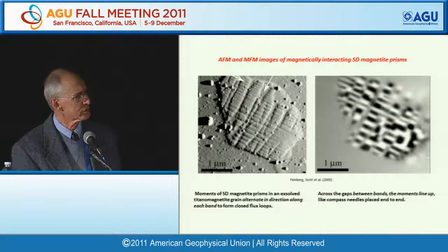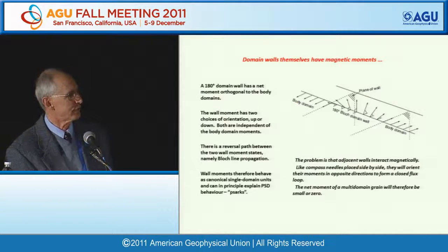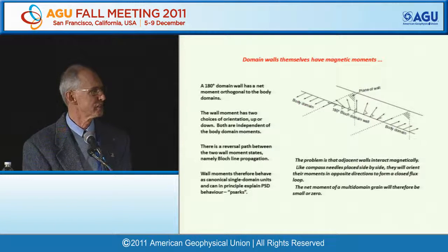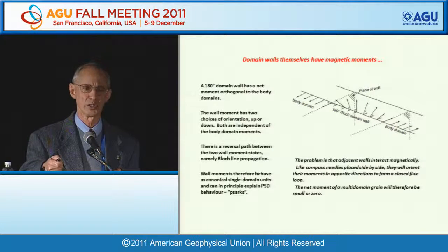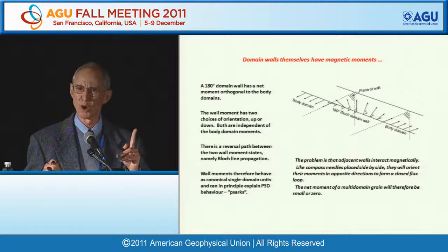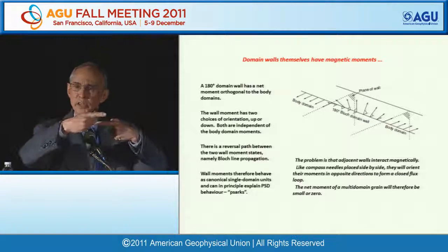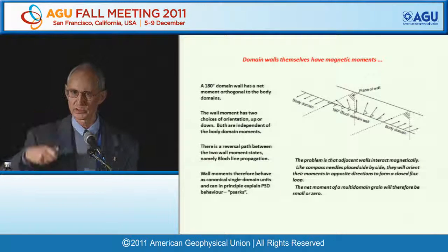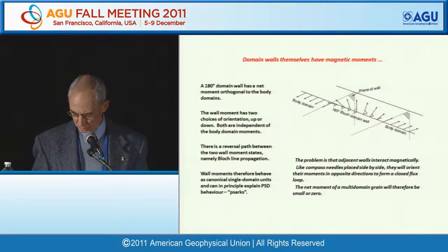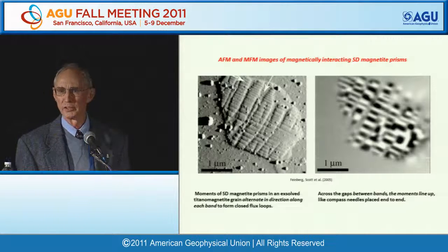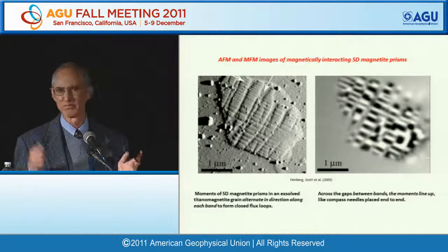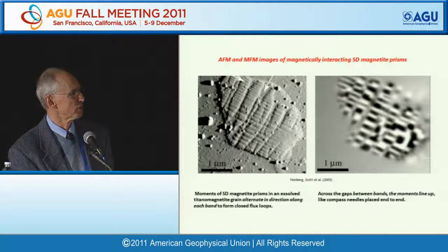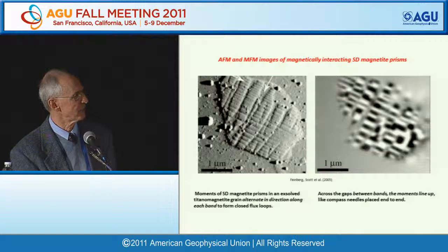Now, the trouble with these things, I forgot to say what the fatal flaw is in all this. The trouble is that the different wall moments interact with each other. So it works fine if you have just one wall moment. If you put in two, they line up in the opposite direction to form a closed flux loop. And therefore, a typical multi-domain grain will have practically no moment. I thought I'd solved the problem, and not at all. It all slipped away.